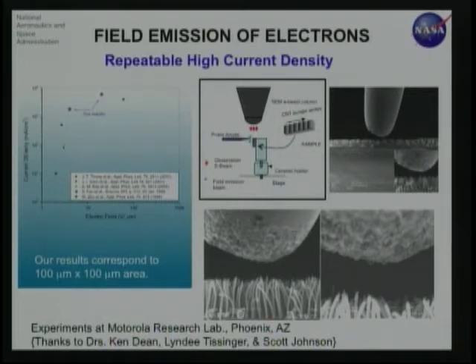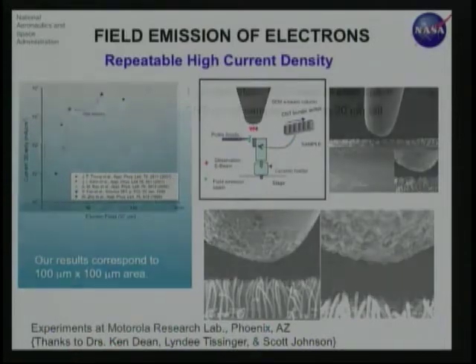So that's one of the reasons why we think that an optimum extremely high current density emission is happening from these. And they also fail because these nanotubes are not very firmly adhered to the surface.